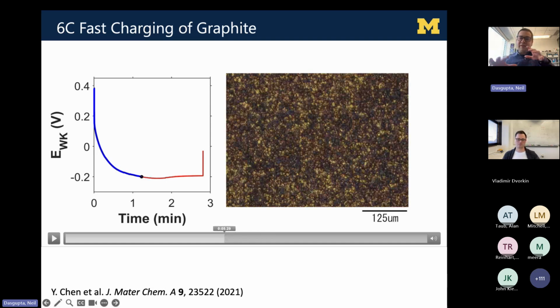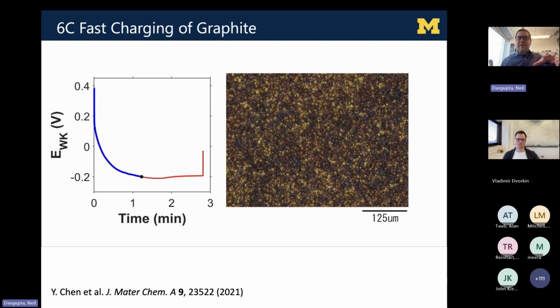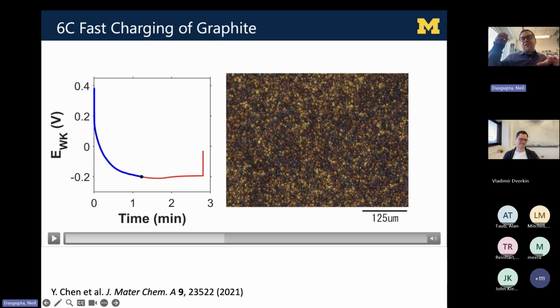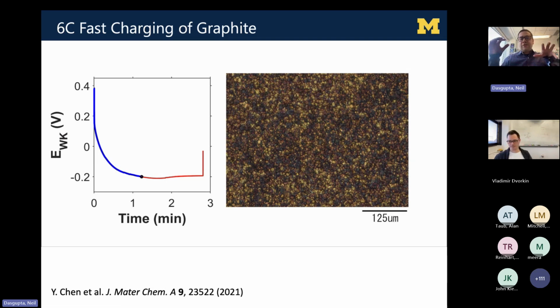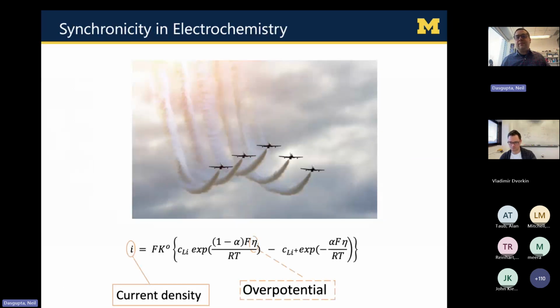This picture right here reminds me of like a calico cat fur, where you can see some of the particles have already reached this gold state very quickly. Others are still in the red versus blue versus gray. So in summary, what we see is when you go to fast charging conditions, spatial inhomogeneity becomes a big challenge. What used to not be a big difference between a slightly bigger or slightly smaller particle or slightly faster or slower one, you could get away with that at slow rates. But under fast charging conditions, what ends up happening is some of them lithiate much faster than others.